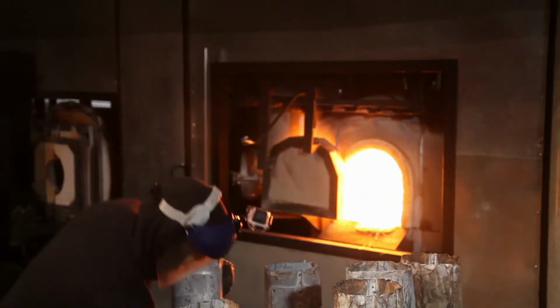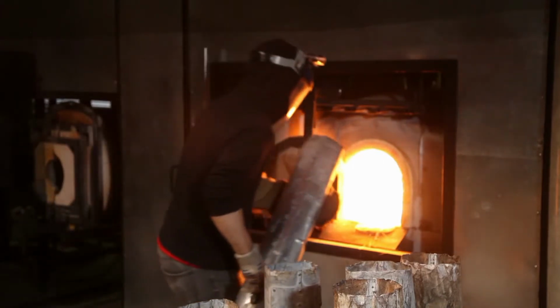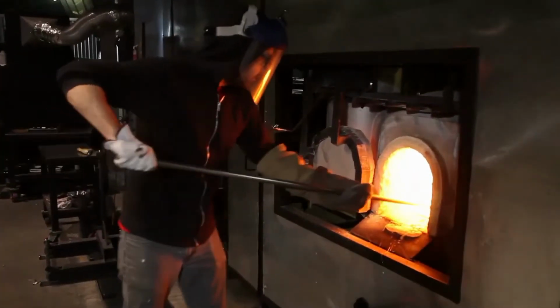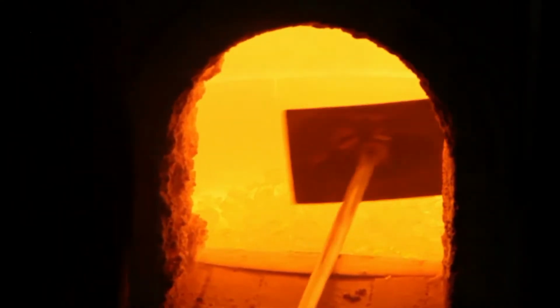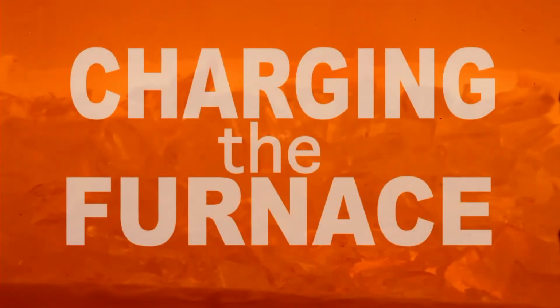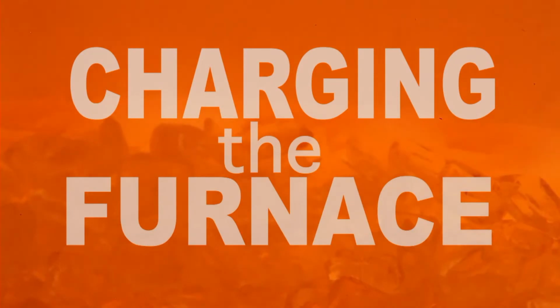The primary ingredient in glass is silica sand, or silicon dioxide. The other two main ingredients are soda, or sodium oxide, which lowers the melting temperature, and lime or calcium oxide to stabilize it. Once the cullet is loaded into the 2300 degree furnace, a rake is used to level the glass for even melting. The furnaces at the Museum of Glass hold approximately 1,000 pounds of clear molten glass and run continuously 24 hours a day, 7 days a week.